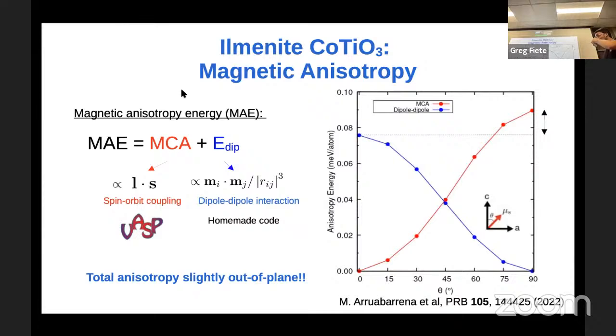These two magnitudes were computed in different ways. The MCA can be computed via DFT, while for the dipole-dipole interaction, we had to make a code to manually compute all of these spin pair interactions. And well, what we did was calculate this anisotropy energy with respect to the theta angle. That is to say, we moved the spin from being out of plane along the hexagonal z-axis, and we moved